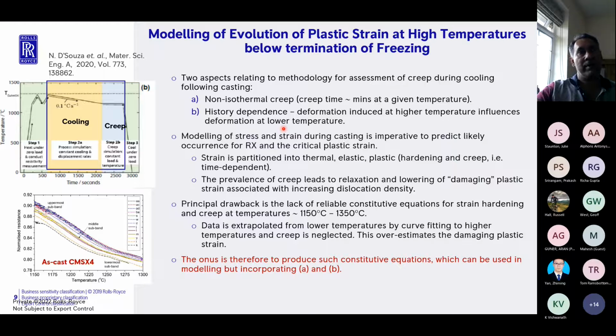So this is not the typical simple creep experiment that one would do isothermally, because there is a path dependence of deformation that influences the evolution of creep and plastic strain at lower temperatures. Very simplistically, the strain is partitioned classically into the thermal strain, the elastic strain, and the plastic strain. The plastic strain is essentially comprised of the hardening strain and the creep strain. What we want to do is find some expressions or constitutive laws by which we can get expressions for the hardening and the creep versions of the strain under typical investment casting conditions, which reflect A and B.